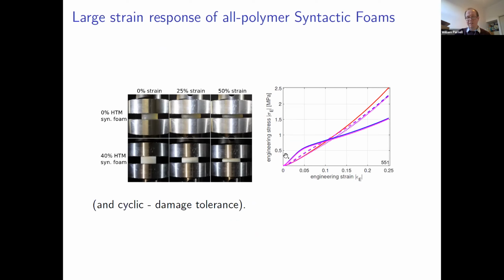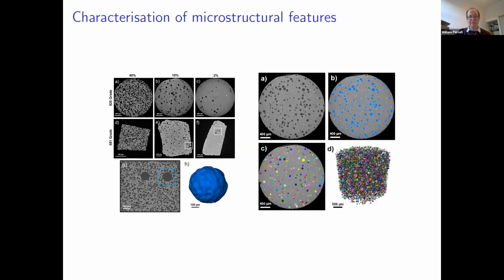So with added filler, you obviously get this increased stiffness initially, but obviously this softness at large strains. These materials are, however, very, very good in terms of their recoverability. So that's a key advantage of them over things like glass microspheres. We've done quite a lot recently in terms of materials characterization. So we've got very good X-ray computed tomography machines at Manchester. And so we're able to do things like characterize microstructure, radius distribution, etc., and also imperfections and defects within these kinds of materials.